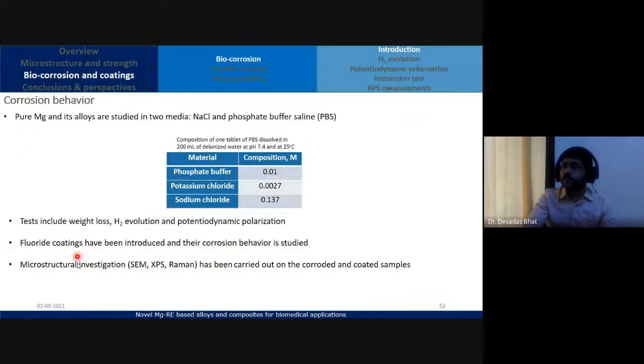Precipitation strengthening also. For corrosion behavior, we perform the experiments in an electrolyte called phosphate buffered saline. Okay, it's in short PBS. This is the composition. Either you can prepare this in the lab, or from Sigma Aldrich you get PBS tablets. So one tablet in 200 ml distilled water will give you this composition, right? And we use this electrolyte to perform different corrosion techniques.